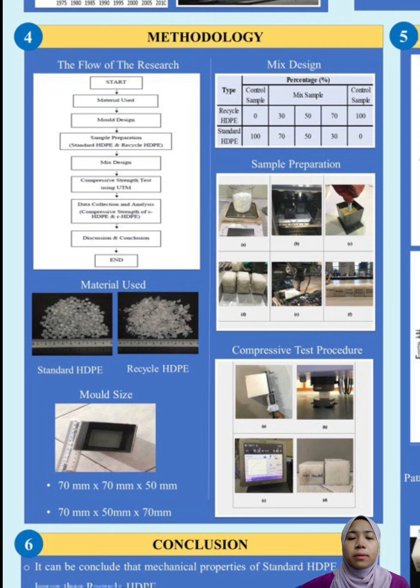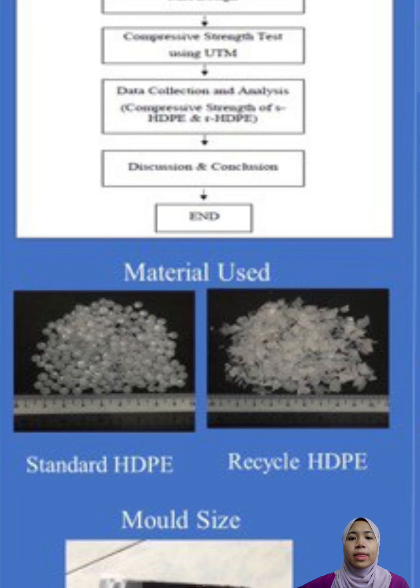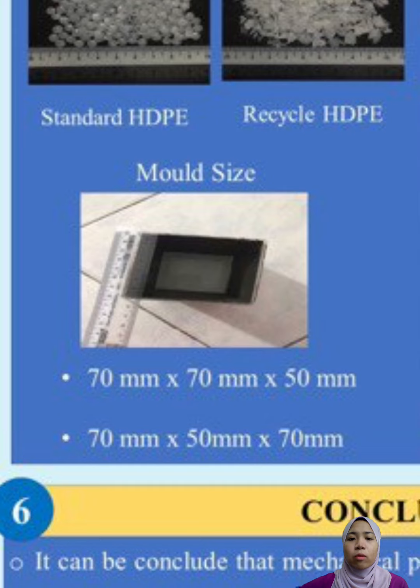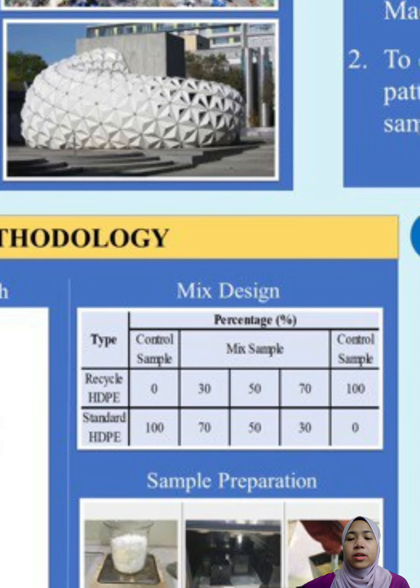The methodology of this study starts with the material used, which is standard HDPE and recycled HDPE. There are two sizes of mold that were chosen in this study, which are 70 mm times 70 mm times 50 mm and 70 mm times 50 mm times 70 mm. In this study, there are 3 mixtures of HDPE plastic according to the percentage. The control sample is needed to ensure the test and the result analyzed are stable.